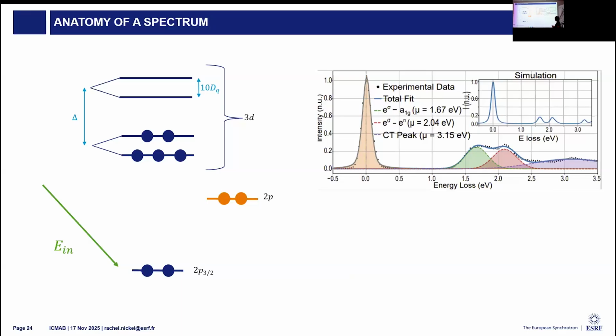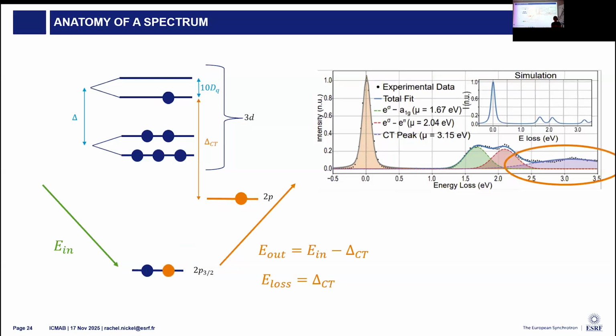The final thing that I have shown in this mock spectra is where we have the excitation, but instead of the electron filling from the iron site, it's filling from a ligand. This tends to form larger bands. So instead of having very discrete localized energy loss, we have the overlap and the hybridization between, in this case, I'm modeling iron and oxygen. And instead of having, say, a 300 meV full width half max, you have these bands that stretch multiple eV.